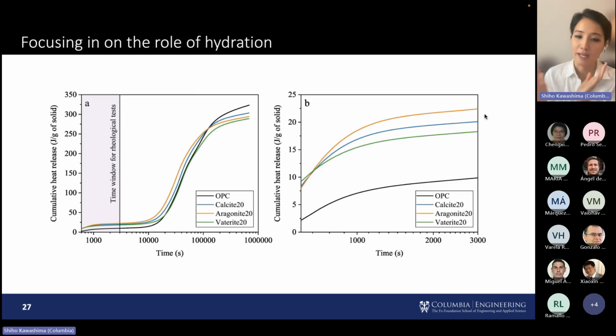And so that points to us that, yes, this is a very early window. And I think there's maybe some discussion on how representative this data is. But for us, for comparative purposes, and we found this consistently in our results, it does indicate that aragonite has higher cumulative heat release than calcite. And that translates to increased formation of early hydrates. And what that means is there's an increase in the solid volume fraction of our suspension, and that would then lead to an increase in static yield stress and other rheological properties as well.